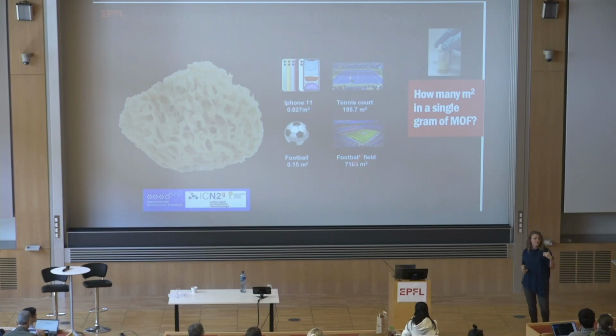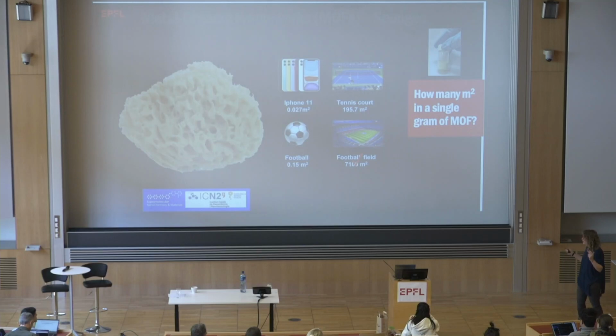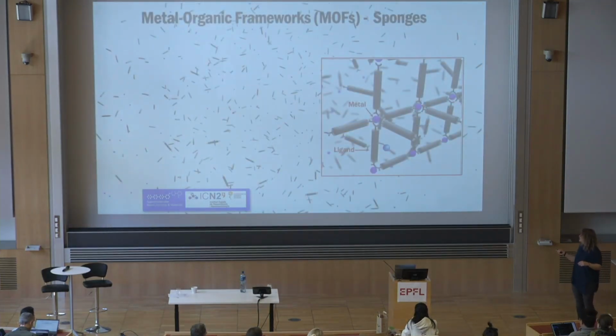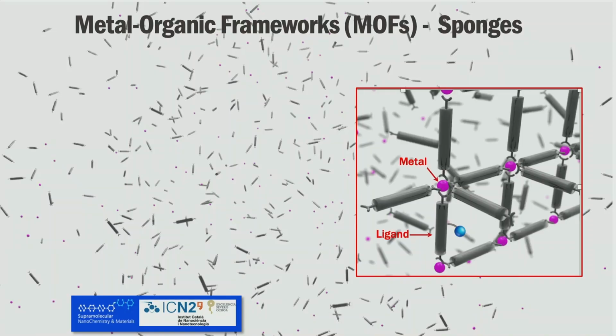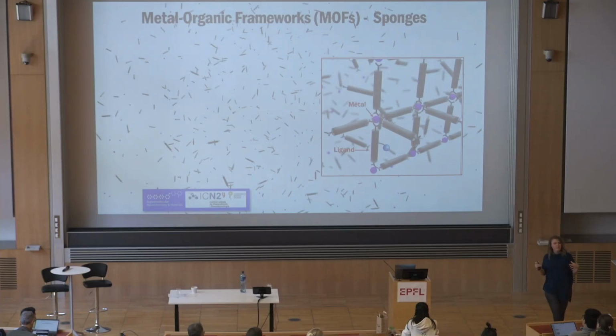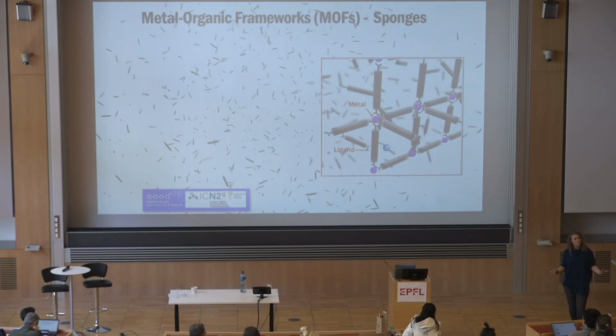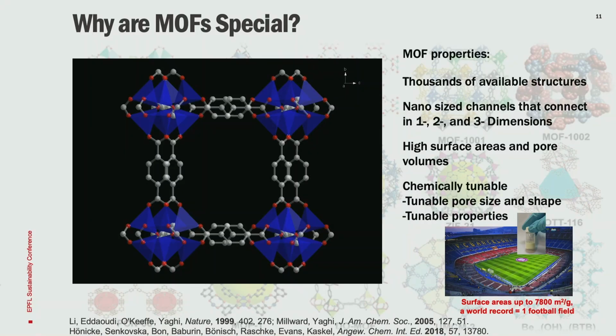And what this physically means is that we can just put a lot of stuff inside them. Their pore volumes are around 5 cc's per gram, or can be up to that. And so, in addition to their high surface areas, the materials have many other interesting factors, and that is their building blocks. So as chemists, we can really alter the metals, we can alter the ligands, and we can use organic chemistry to change the functionality that's present on the backbone inside the material. And this is physically how we tune those materials to get them to interact with certain targeted species that we want to remove from gases or from liquids. Okay? So these materials are quite versatile.